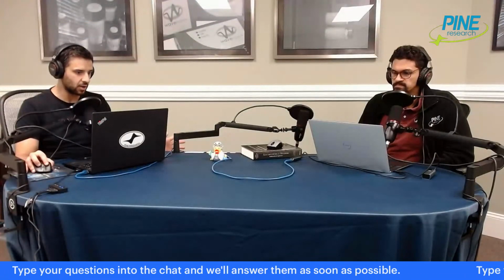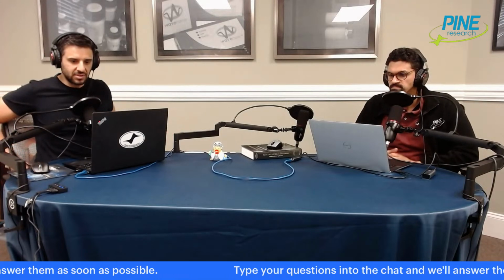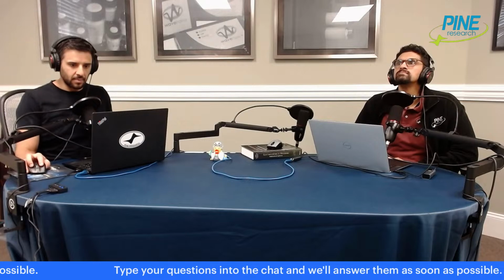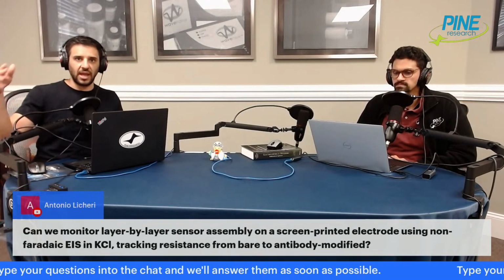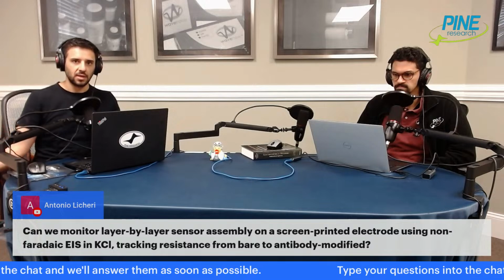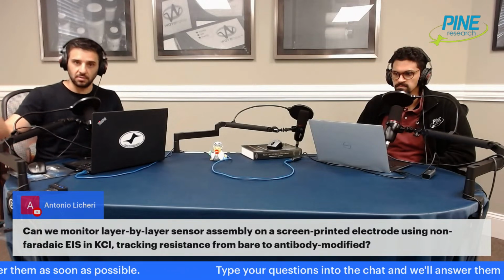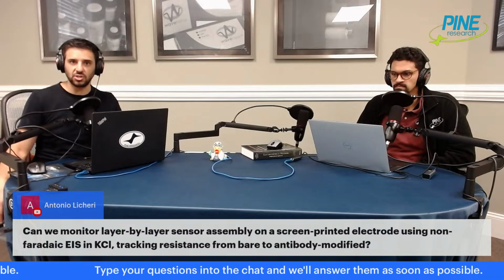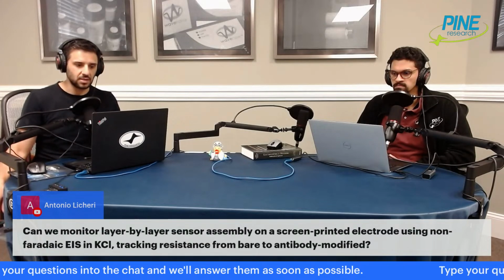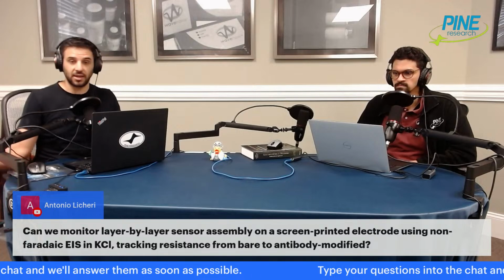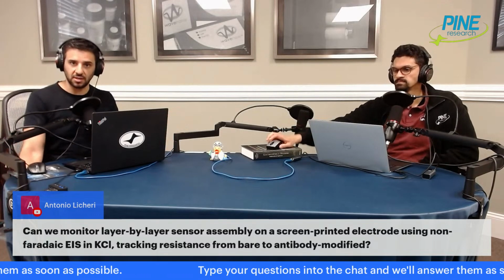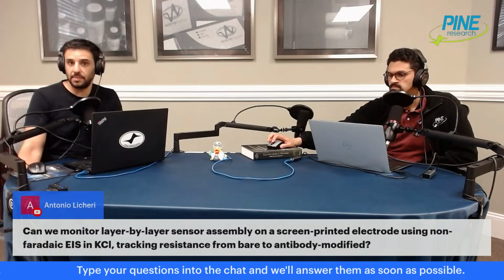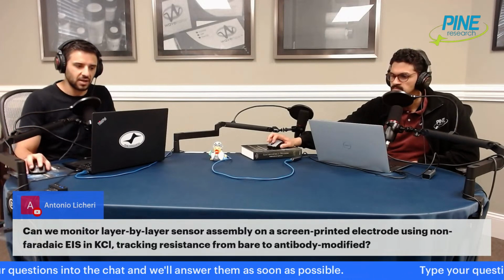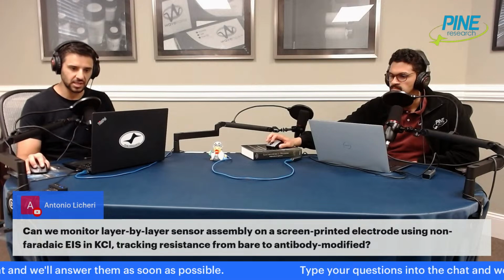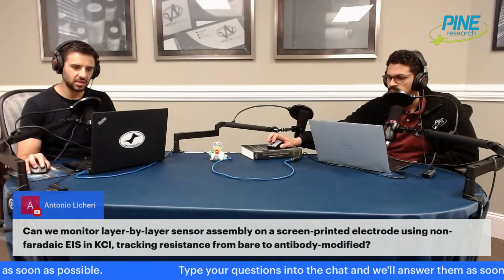And so, yeah, for sure, one of the real benefits of impedance, for instance, is that you can have this multi-step layer by layer assembly. And as long as your electrode between each step, between each process is still intact, you can run a quick impedance experiment on it and check the response and see how the resistance changes. Heck, you can see how the capacitance changes, how the diffusional behavior is changing. The OCP might shift. Like all sorts of things are going to happen when you modify the electrode. So that's just one example for you, but absolutely, this is something that you can do.